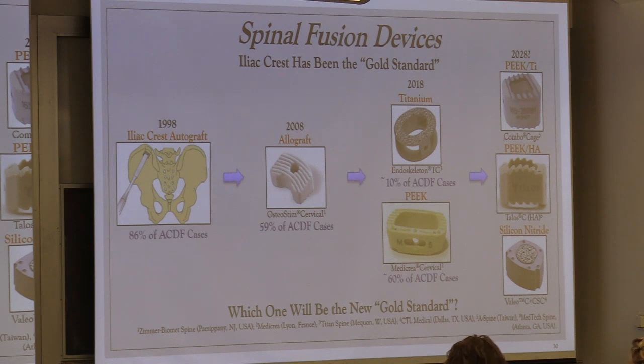And then they went to allograft, and allograft is cadaver bone, so it's dead bone. They harvest the bone, and then they machine it, and they sterilize it to a certain extent, but it still has some biotic capability, so they thought that was good. But of course, it's in quite limited supply. But you can see that it was about 60% of all cervical cases then. And then by 2018, this had switched all over to abiotic materials, including PEEK and titanium as the primary materials. And they were about 70% of the overall market at that point in time.